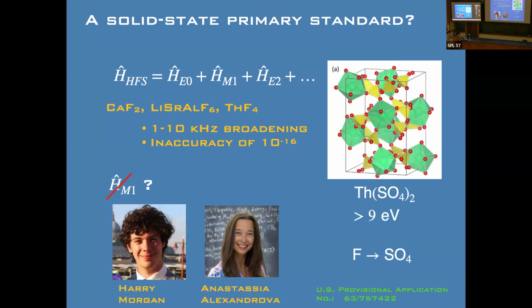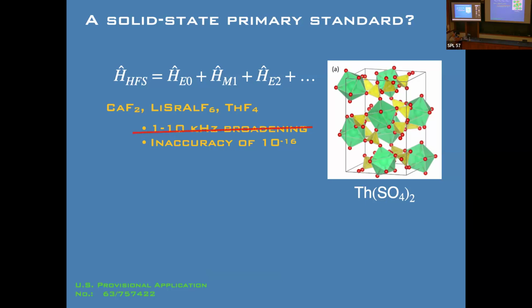And so this crystal, thorium sulfate, they've done high-level GW calculations on, and the band gap is at least 9.1 eV, probably a little higher. And so that's big enough because we don't have to worry about any defects being created because thorium-229 dopes into that without creating a defect. There'll be no states in the gap because thorium's already part of the cell. Okay? These have no nuclear spins. This just goes away.